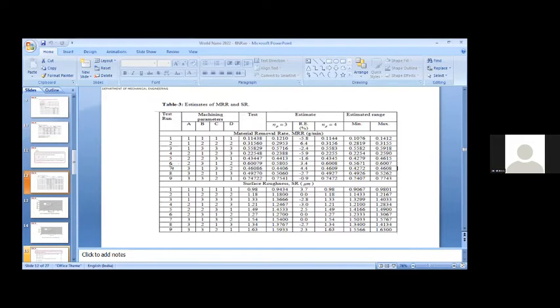You can see this is the test result. Only 3 process parameters have been considered. The relative error between the test and the estimate is below 7%. If you also take the error term into consideration as the D parameter, the exact result is coming. From this, we can find the estimated range from minimum to maximum. All the test data is falling within this range. Then by changing the levels of the parameters, we will be able to find all 27 possible combinations.